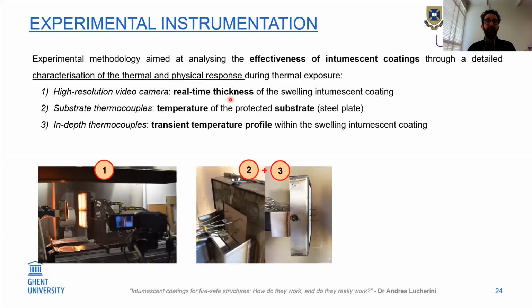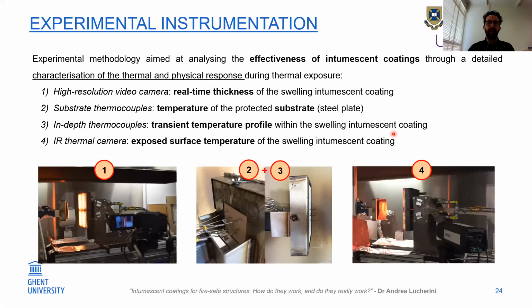Then I also applied a series of thermocouples placed at the substrate to quantify the evolution of the temperature of the protected substrate, so the temperature of the steel plate, and also in-depth thermocouples. You can see here the transient temperature profile within the coating while it was swelling. So what are the temperatures inside the coating while it is swelling? And finally, I also used an infrared camera to quantify the temperature at the exposed surface of the swelling coating.